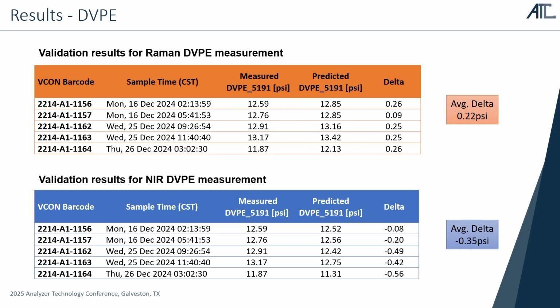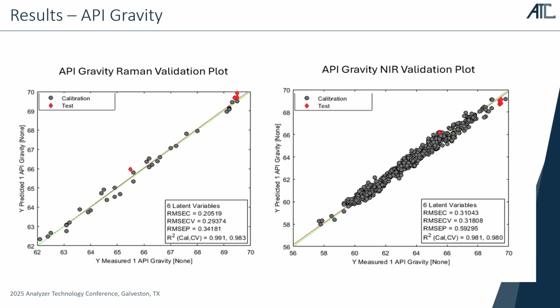So overall, here's just a selection of samples and the deltas between the measured value and the predicted value. Overall deltas for the Raman, 0.22 psi. For DVPE, that's again the difference between the laboratory and the analyzer value. And for the NIR, the average delta was 0.35 psi. And I would argue the absolute value is what matters, not whether it's above or below, because that's essentially random. So a little bit of a difference, but not a huge difference.